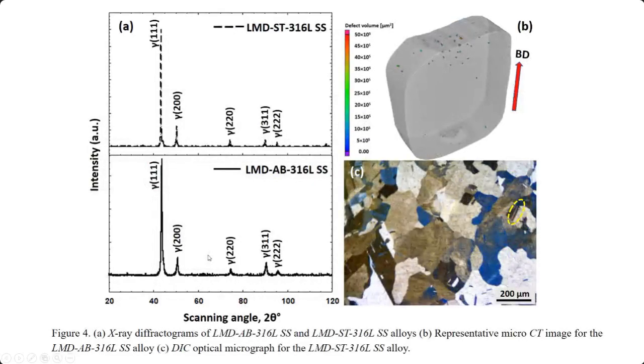So what we did in this case is, we have such variation in the microstructure, and to get rid of that we have solutionized them. We manufactured the component by additive manufacturing, and then used the conventional heat treatment procedure just to modify and homogenize the microstructure.